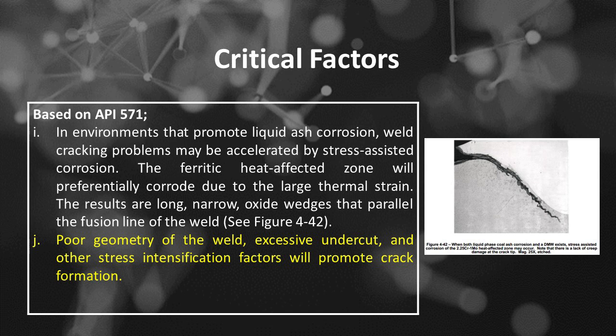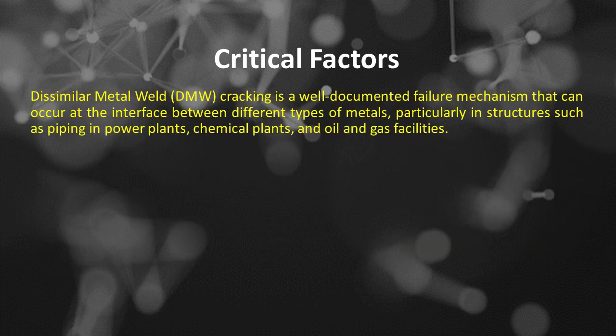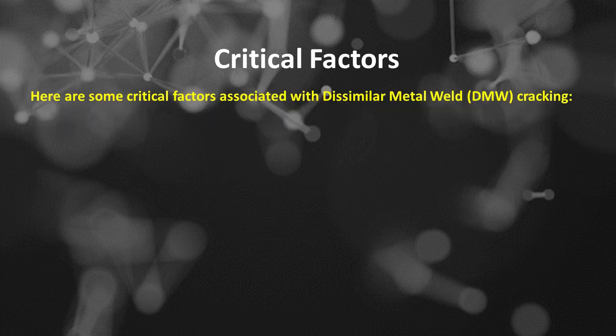Item J is poor geometry of the weld, excessive undercut, and other stress intensification factors will promote crack formation. Dissimilar metal weld, DMW, cracking is a well-documented failure mechanism that can occur at the interface between different types of metals, particularly in structures such as piping in power plants, chemical plants, and oil and gas facilities. Here are some critical factors associated with dissimilar metal weld, DMW, cracking.